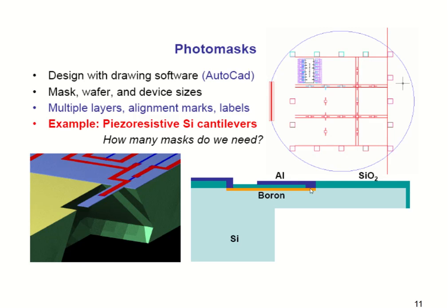So this boron diffused area is a conductive silicon layer, and then you put in dielectric material like silicon dioxide, and then you pattern these two areas to make some holes, and then you have a connection with the metal layer like aluminum. That's the build up, and then to make this cantilever structure, you actually have a back etching done, so you have some space underneath the cantilever. So that's kind of the MEMS device you may want to have.